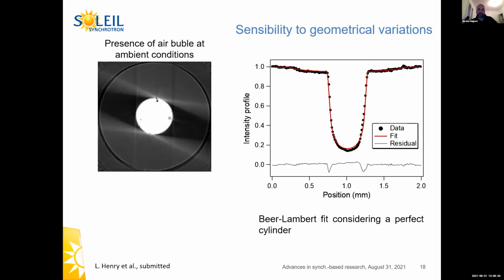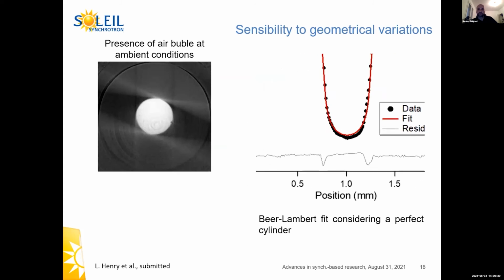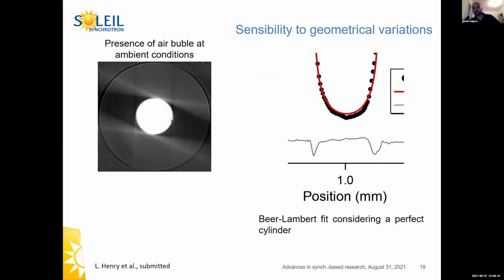Here I'm going to have a look at a specific example. If we look at this fit, we see that the fit is not very good, because the fit in red considers that the sample is a perfect cylinder. But when you look at the high-speed tomography that we could do at the same time, you can see that there are bubbles inside the sample.